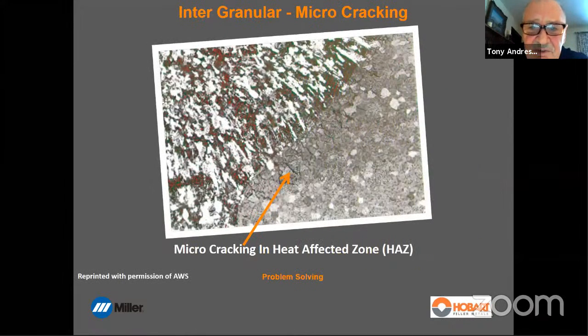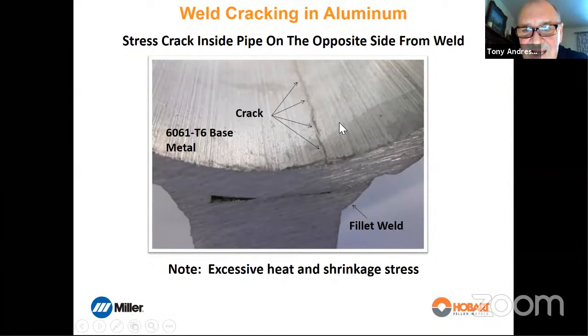All right, some other cracking: underbead cracking. On the heat treatable alloys, if we overheat them, particularly in multi-pass welds, we can cause this intergranular cracking beyond the fusion line. Not uncommon, so we've got to watch our heat input. Now, this is cracking inside a 6000 series. We have a weld here that's deep, the penetration goes way back here. So we're getting this micro cracking on the inside of the weld.